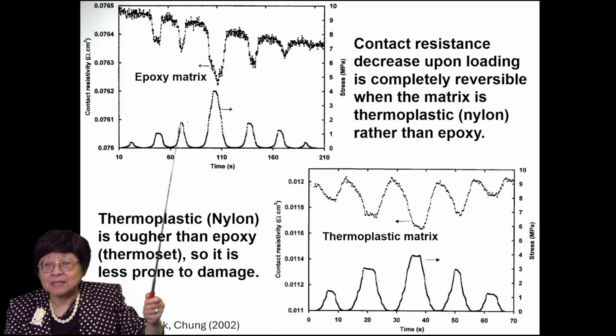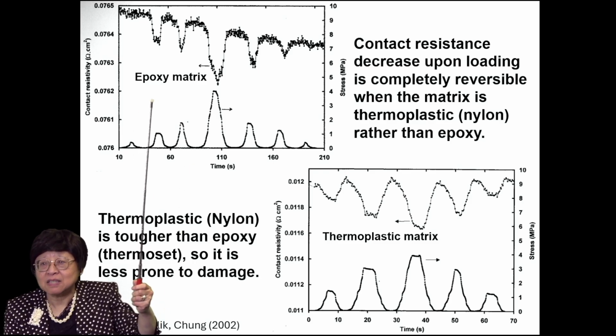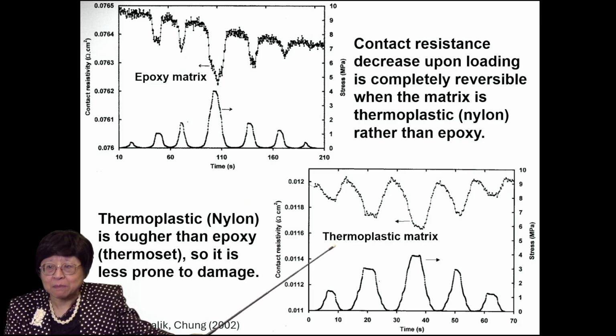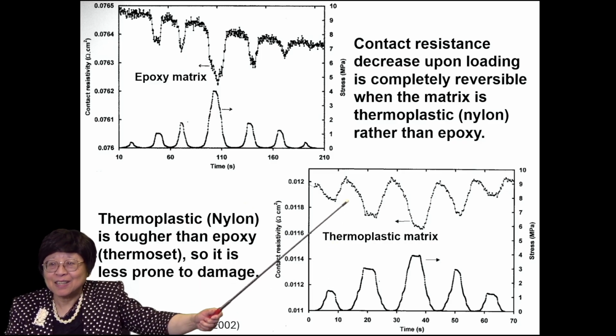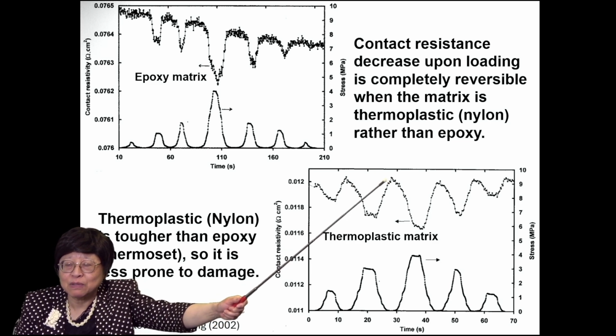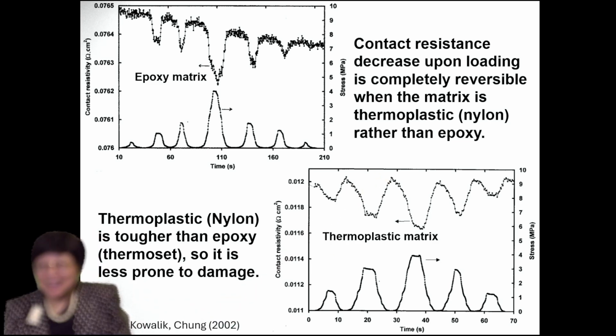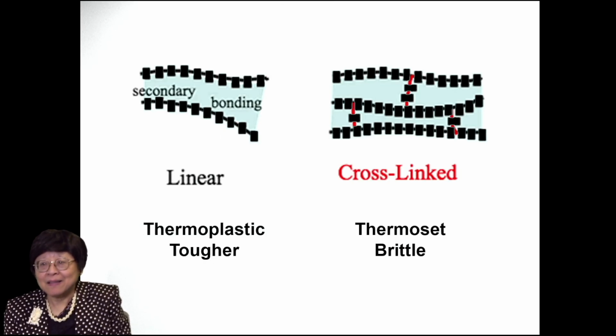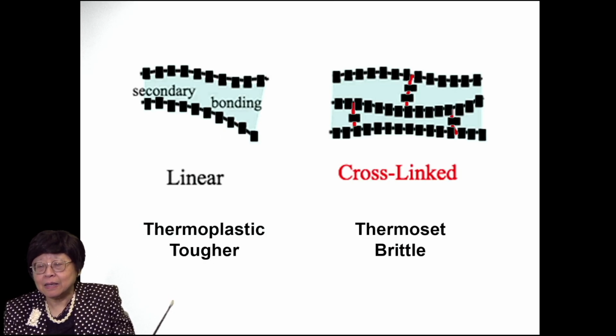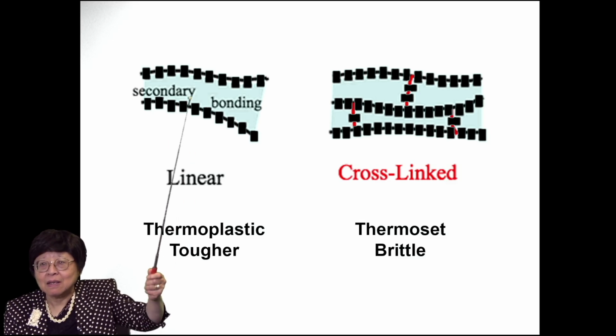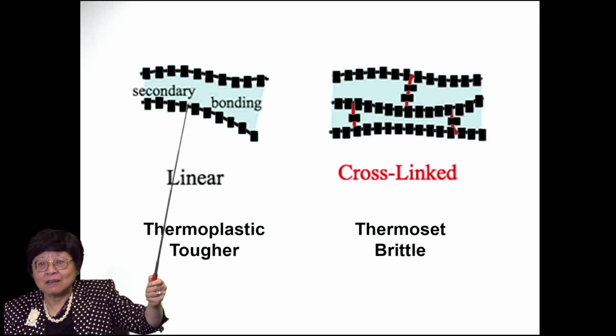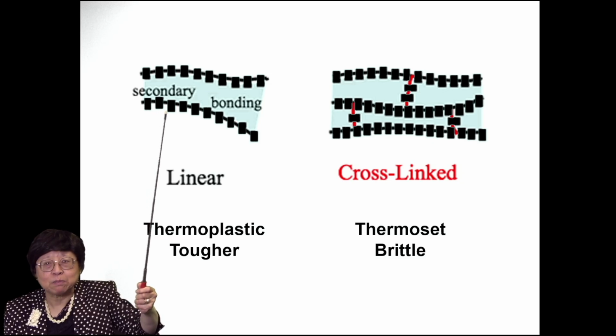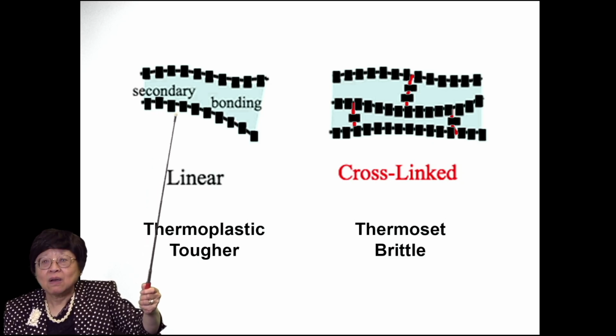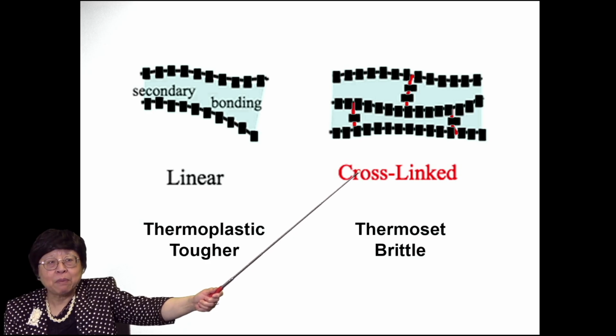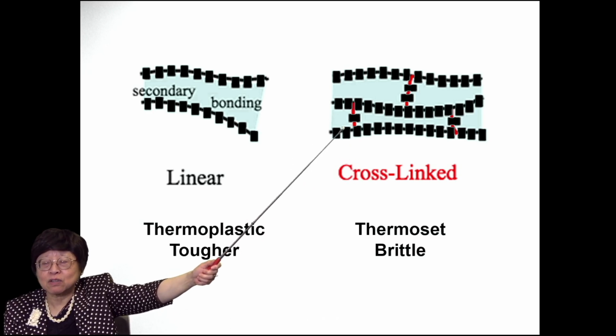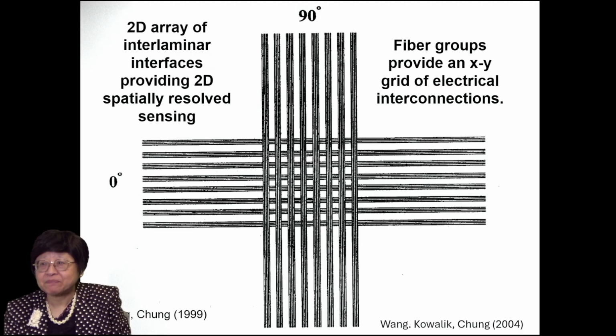However, if we replace this very conventional epoxy matrix with a thermoplastic matrix, such as nylon, see, upon unloading, the resistivity returns all the way back. Okay, that's very good. And it's because the thermoplastic, like nylon, has polymer chains like that, and they can slide easily with respect to one another, so it's pretty tough or ductile. But for the epoxy case, it's brittle because of the cross-linking between the chains.